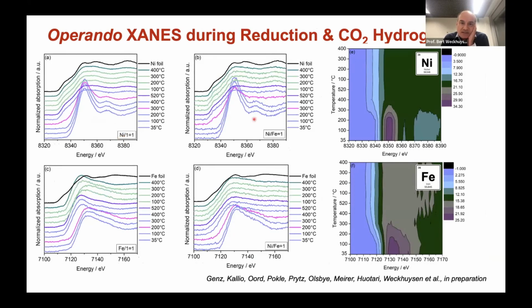This is the nickel catalyst. This is the nickel iron catalyst. Here I show you the nickel edges. And here I show you the iron edges. What we first do is we heat it up, reduce it, then cool down, and then do CO2 hydrogenation. So two phases. You heat it up, you reduce it, and then you run the catalysis with CO2 and hydrogen. Here you see this waterfall type of plots where you have temperature as a function of the energy for nickel and the iron. What you can notice is that when you have iron around, it will influence the reduction. While for the iron edges, you see changes, but they are much more deconvoluted.